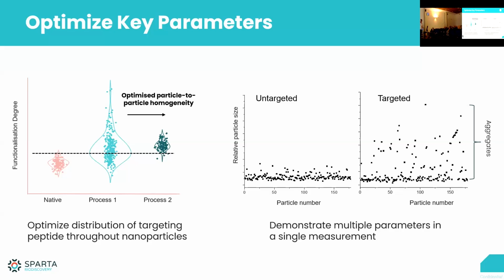And a secondary measurement that we do at the same time, where you don't have to change anything in the settings, is based on looking at relative particle size of these particles. So the native formulation was very nice. We see a relatively tight population, a couple of particles a little bit bigger. But when they had a lot of targeting ligand in that process one, they saw that it actually caused aggregation as well. And that's pretty common when people are adding that.